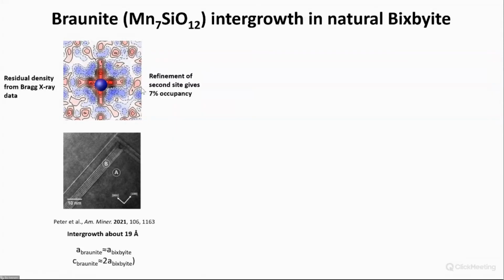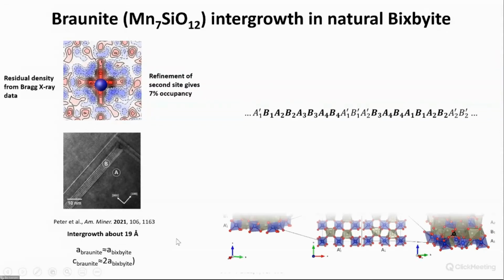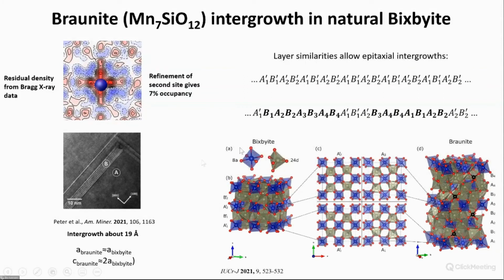Well, the electron diffraction has shown that Bixbyite, when it's from natural sources, will have these inclusions of another mineral called braunite, a manganese silicate. And Bixbyite and braunite have almost the same a-axis and just a doubling of the c-axis. So if you look at the structure here, the A1 layer of Bixbyite is virtually identical to the A1 layer in braunite. And again, one of these three layers is virtually identical.